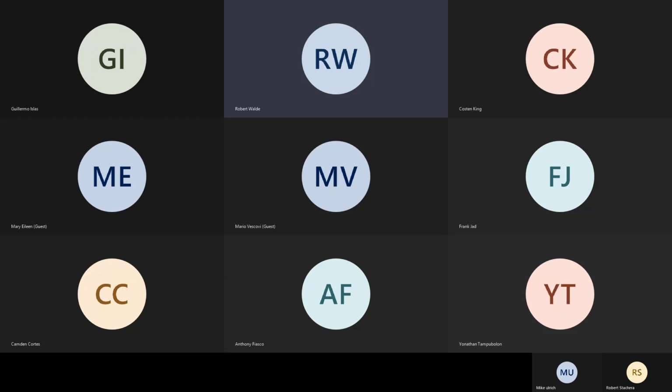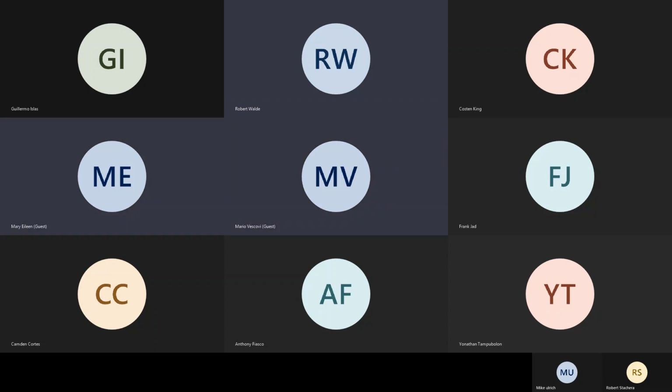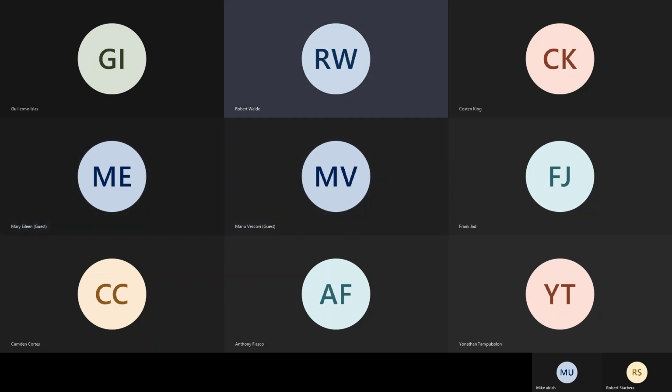And with green rebar, we get a response back. People say, well, we're using green rebar now, and it doesn't really have any negative impact. Well, the problem is, of course, the green rebar coating, which is epoxy paint, is protecting it from the concrete. And what we've found is that where you get damage on the rebar, you create a cathodic site. You can actually have corrosion right underneath the coating of the rebar corroding. So those were a couple of things just to add. That one picture that you did see was of green rebar.